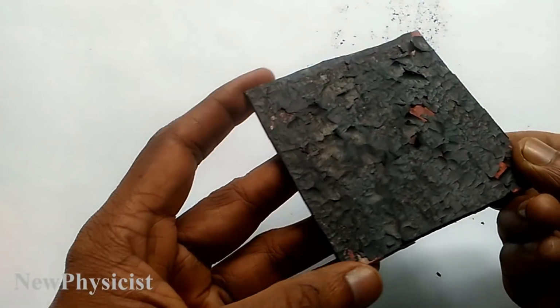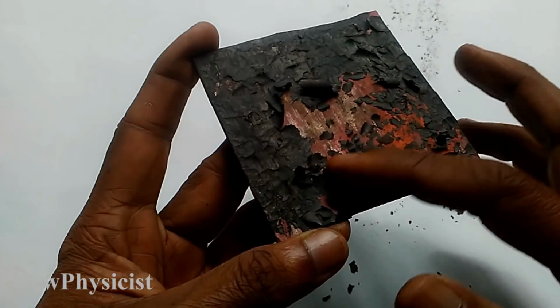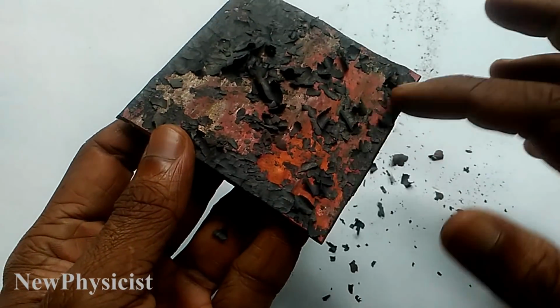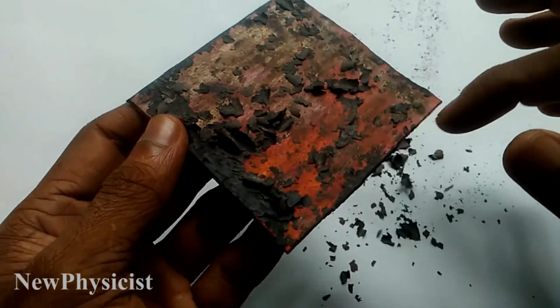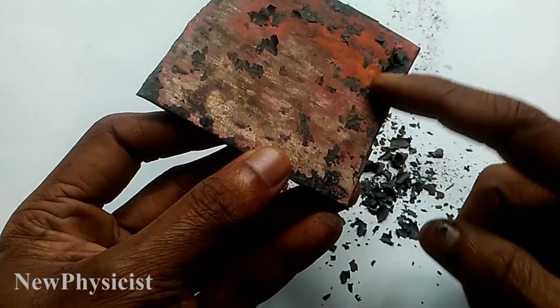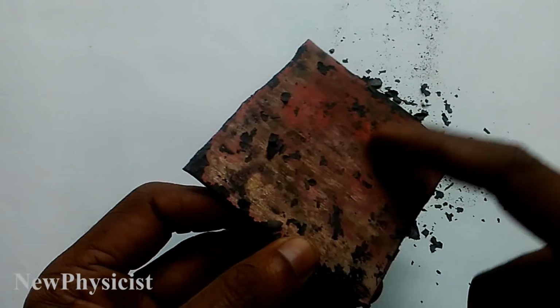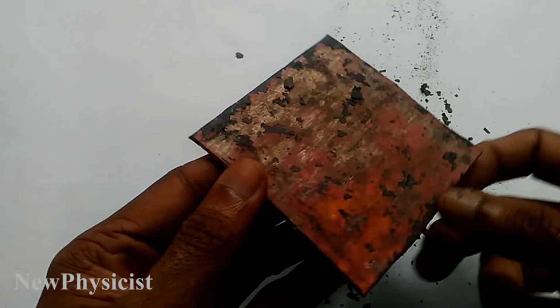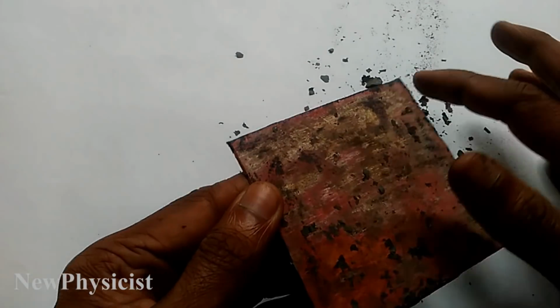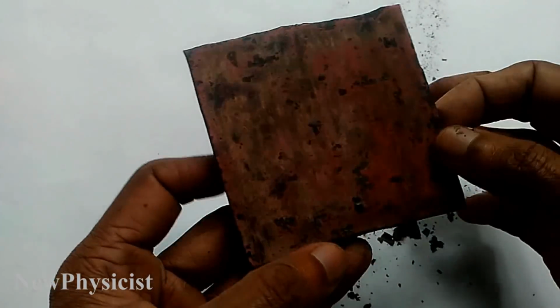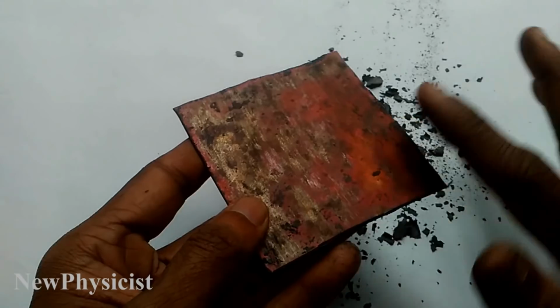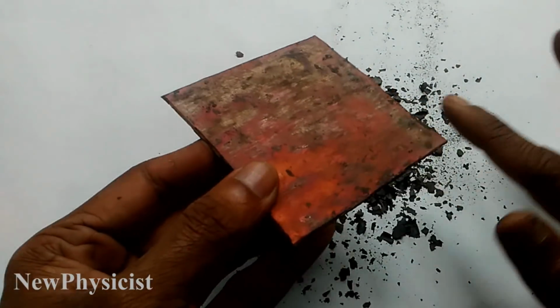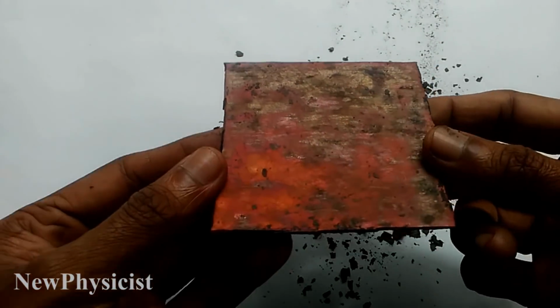A thin layer of cupric oxide will remain on the copper, covering up the cuprous oxide layer that needs to be exposed. Keep in mind that cuprous oxide is a semiconductor and must be exposed in order to make the solar cell function. And don't try to remove all of the black cupric oxide. It may damage the cuprous oxide layer. Okay, the semiconductor is ready.